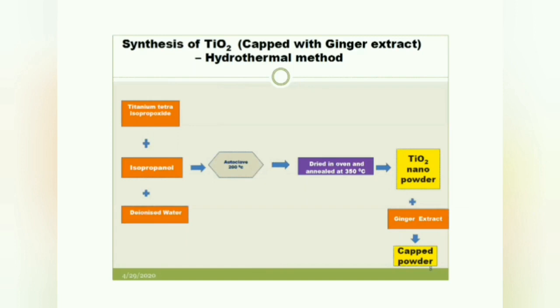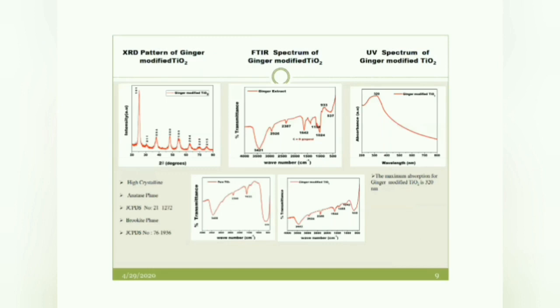Then I take some 2 ml of titanium dioxide nanopowder and mix it with a magnetic stirrer, then go for the centrifuging process, and then the drying oven. Then I get the ginger modified titanium dioxide nanoparticle. It's a surface modification. From the XRD pattern, I can see the 101 peak around this anatase phase.